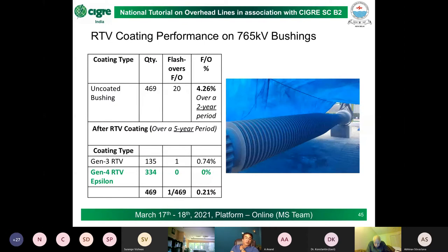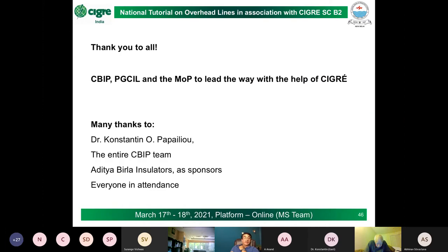What we found here between the uncoated bushing and the coated bushing is that there was approximately a 4% flashover per 2 year period, whereas after the coating, for Gen 4 coating, this came down to 0% over a 5 year period. So I would say generally they are highly successful here.